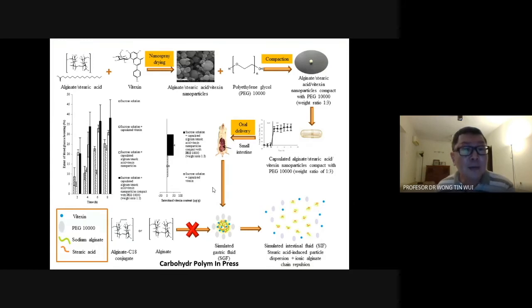Now, in the same diabetic project, we also look into small molecular drugs. In these studies, we isolate the vitexins from Ficus deltoidea, which is a natural herbal plant. We mix the vitexin with alginate and stearic acid and spray dry it into nanoparticles. Knowing that nanoparticles have a large specific surface area, they tend to release the drugs in the